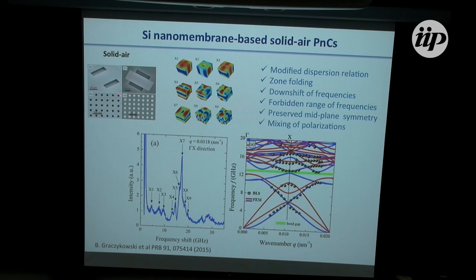Yes. So having this type of solid air, or the holey ones, we see that there is a modified dispersion relation. There is some folding. The frequencies crash or go down dramatically. There are frequencies that are forbidden, so we actually open regimes where there is no phonon propagation. We preserve the mid-plane symmetry, and we have a mixing of polarizations, which is happening here, most clearly perhaps in this regime.